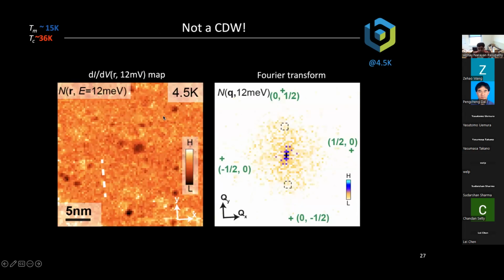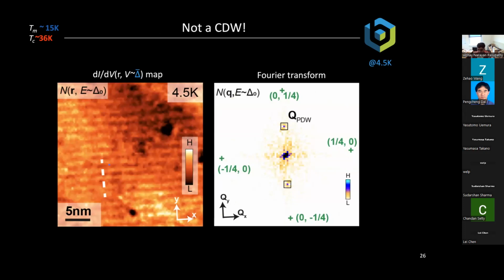Okay, so now the first thing that I want to try to convince you is that this phenomenon that we're seeing is not a charge density wave. So a charge density wave is also something where the electrons break the translational symmetry of the crystal. But a charge density wave affects electrons at all energies. And this is because when you have a charge density wave, the atoms physically move. And when the atoms physically move, they're going to give you a new periodicity, and electrons at all energy scales are going to respond to this phenomenon.